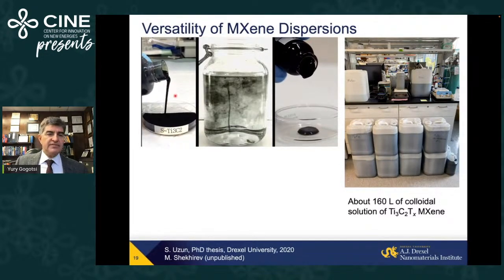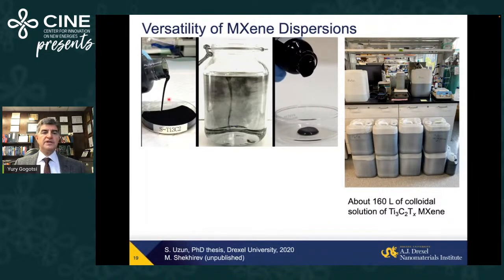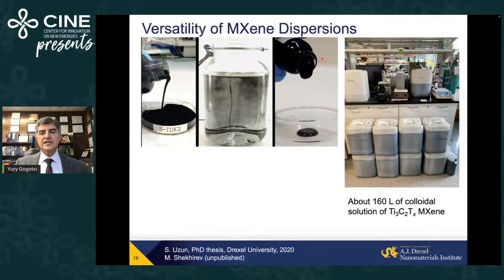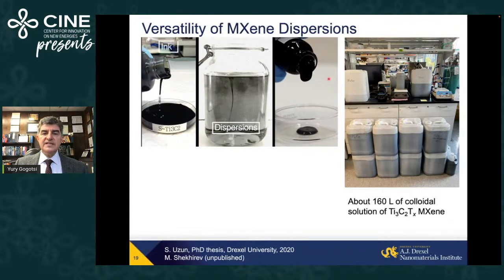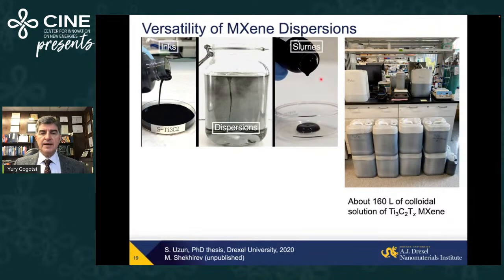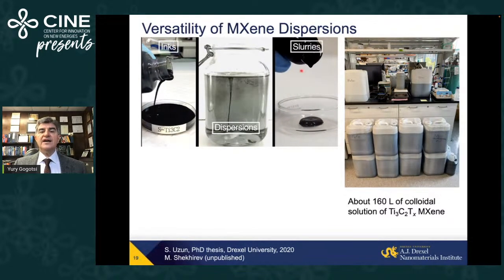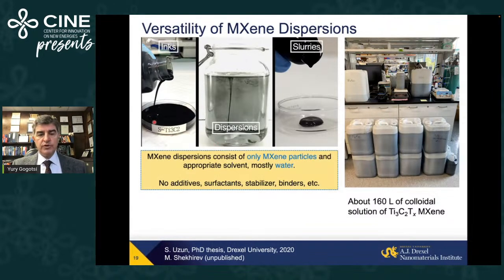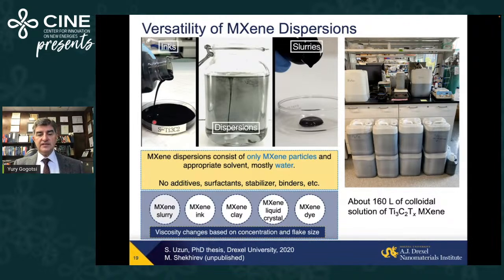This is a 10-20 milligram per milliliter solution, which can be used for inkjet printing. This is a liquid crystalline solution, maybe 100 milligram per milliliter or more. Our flakes align. This was the one used to make the films that I showed you. And this shows how we can, for example, make large volumes of colloidal solution in water. Moreover, no additives, surfactant, stabilizer, or binder needed.